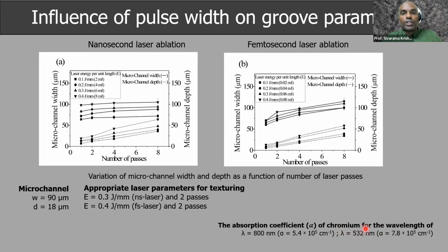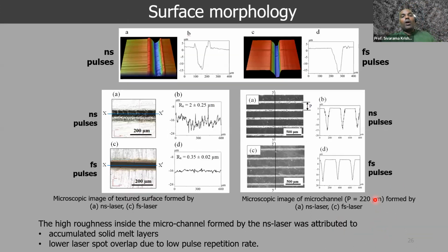So this holds only so much importance in one sense. The surface morphology of the grooves which we made is very evident in these optical profilometry images. We can clearly see that there is a bit of a recast bump on the sides of the nanosecond laser formed grooves, whereas in the case of femtosecond laser formed grooves, this is fairly flat. This is evidence that the grooves are much less collaterally damaged, or almost none, when we use femtosecond laser pulses.